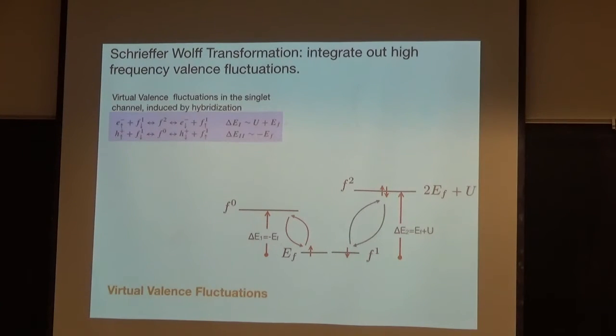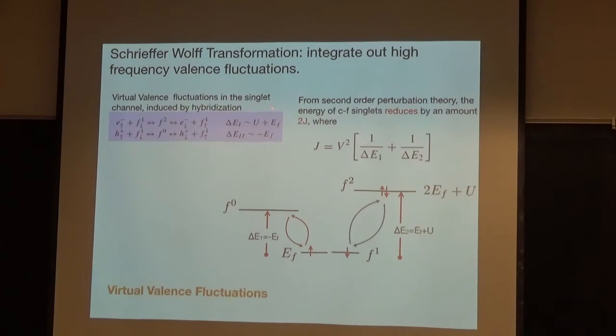And one way of thinking about this is the following, is that an electron can hop into an F1 state and form an F2 state, or a hole can hop into an F1 state and form an F0 state. These excitation processes are both very energetic, and they only occur when an electron scatters in a singlet state with the F electron. And so this means, from second order perturbation theory, that the energy of a CF singlet is reduced by an amount given by V squared over the excitation energy. When you work it out in detail, it's 2J.